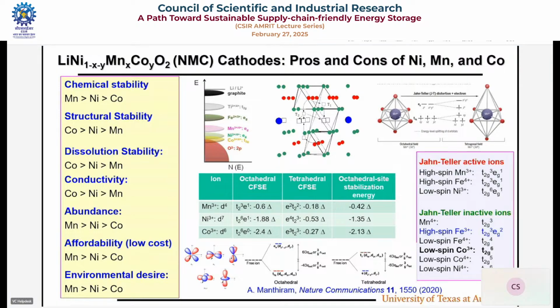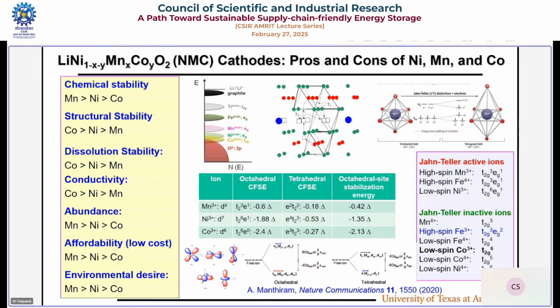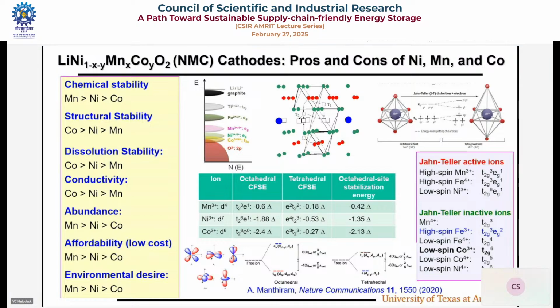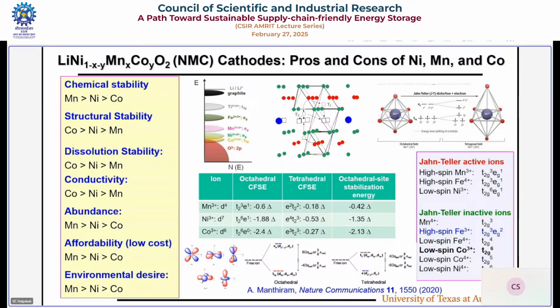That's the path. For that, this is my own contribution. Nobody ever did. This is what comes from my teaching. I was teaching 4 years. All this coordination chemistry and crystal field. So, you know crystal field splitting, when we have a free ion, all d orbitals will be of similar energy. The d orbitals have different orientation. 3 of them have their lobes in between the axes. The other 2 have lobes along the axes. So when you have negatively charged ligands, oxide or even water coordinated, they will perturb these orbitals differently.